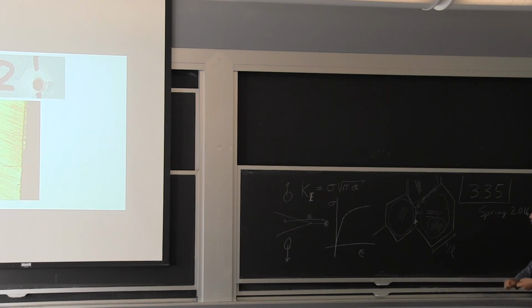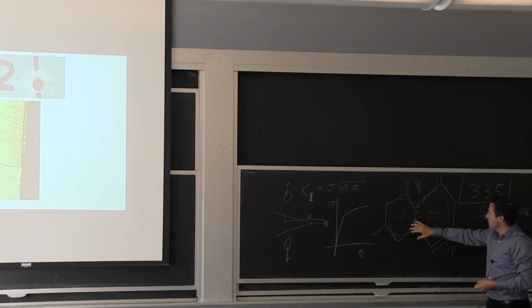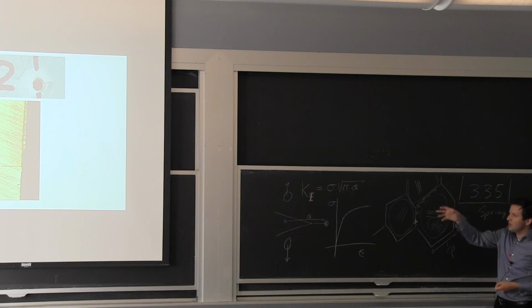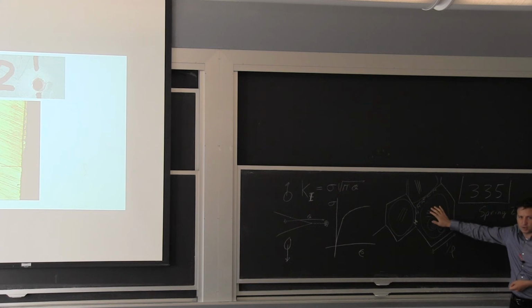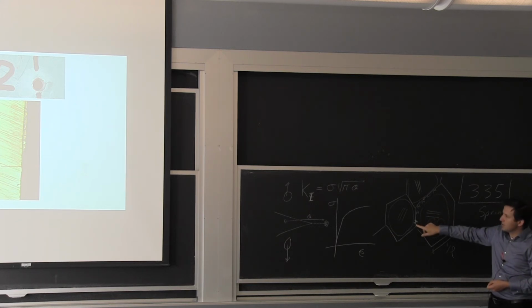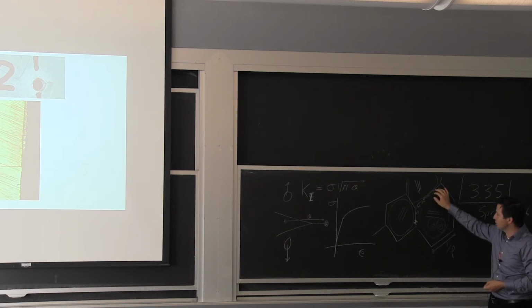So now you're going into a very different process. We went through all this difficulty of forming the martensite. We're preventing here deformation in the grain. And if in service we have the generation of hydrogen, sometimes it's in processing also. If you do an electrochemical deposit of the nickel over a coating, you can get hydrogen in your microstructure. So this becomes stronger, this becomes weaker,